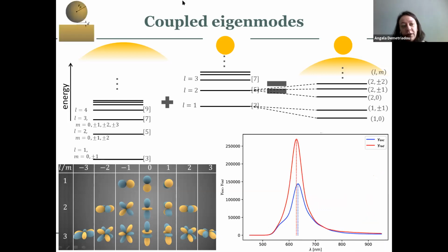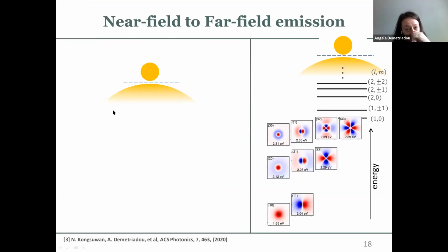And the same thing happens for the nanoparticle on mirror. So again, this is the radiative decay rate and the excitation rate in blue. The difference between the nanoparticle on mirror and this system here is that now my higher order modes, which were discrete for the very large nanoparticle, for the sphere, just become continuous. And it is what people refer to as the propagating SPPs, but the same selection of modes and polarization with the incident polarization remains within the system.